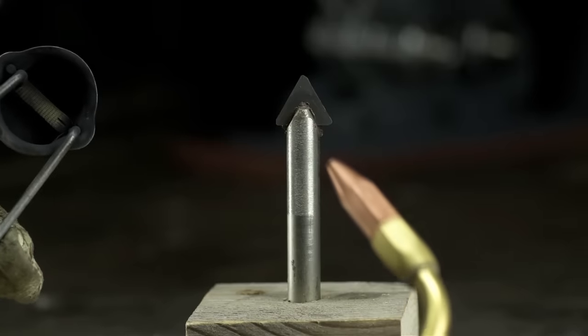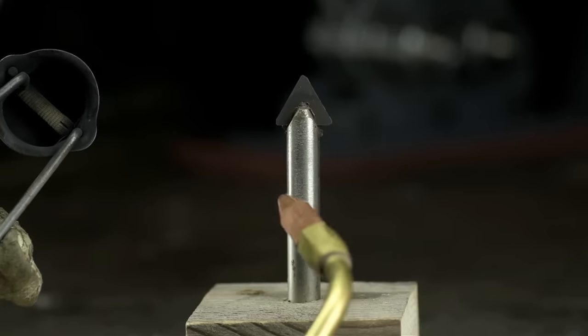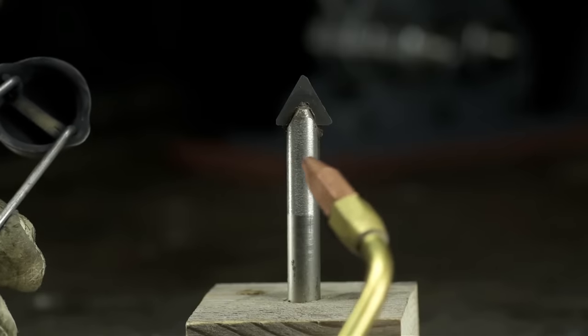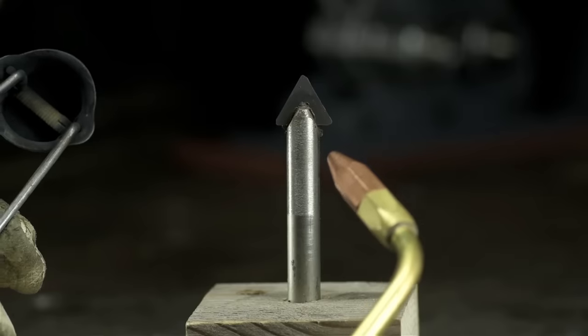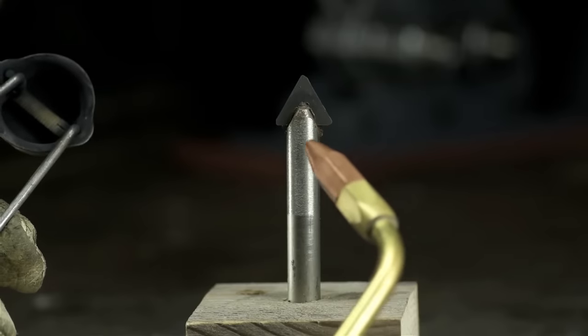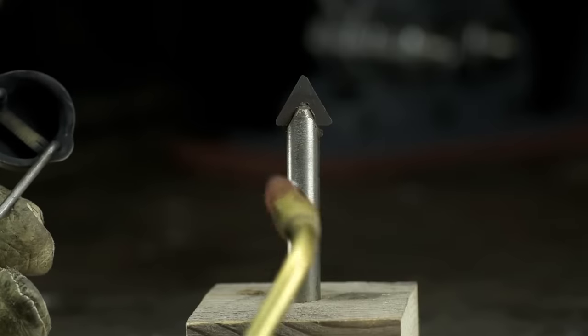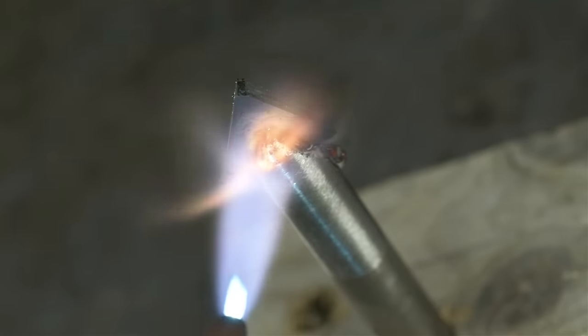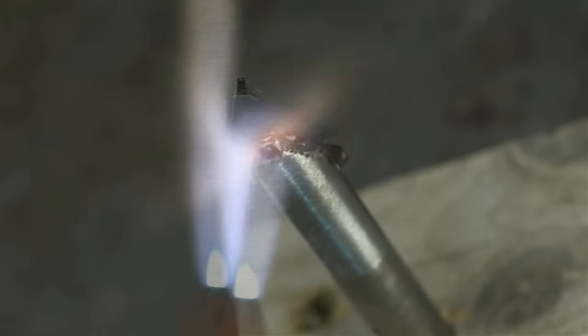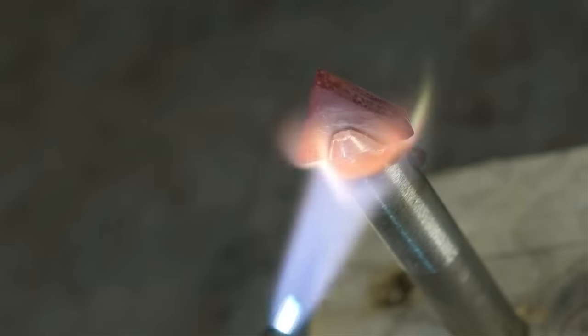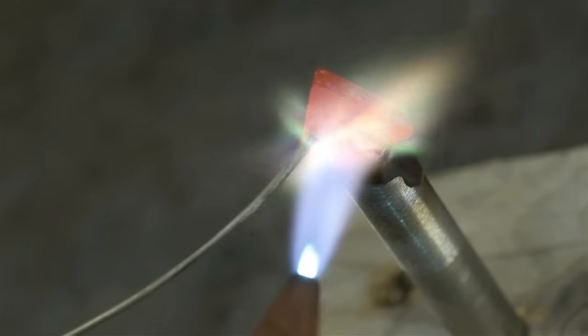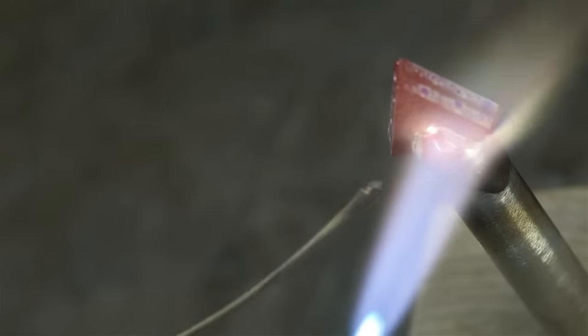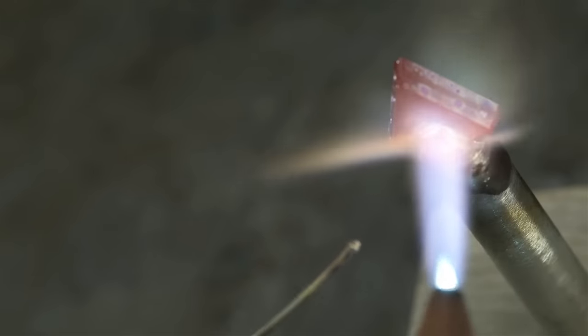You can do this in your vice, of course. I just put a hole in this wooden block. It's easier to film. Not to mention the fact that my vice is currently hidden under 50 pounds of junk. Now for heat, I'm going to be using oxyacetylene. I think that's really what you want for silver brazing. For something small, though I've never tried it, you may be able to get away with like map gas, stuff that comes in the yellow bottles. You'd have to check the temperature rating, I'm not sure. But for small stuff, you may be able to get away without using oxyacetylene. Now typically, you want a much larger tip than this. Again, depends on the size of work you're doing. You don't want the same kind of flame you'd use for welding. You want a big, soft, easy-going flame. Remember, we just want to get the base parts hot. We don't want to melt them.